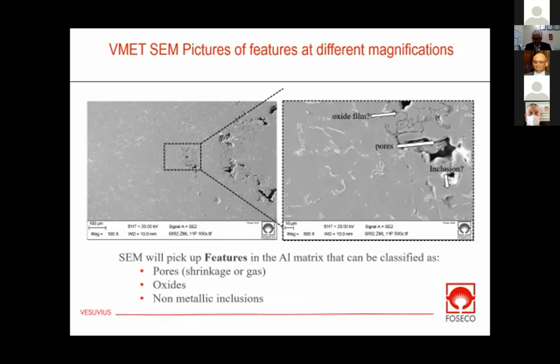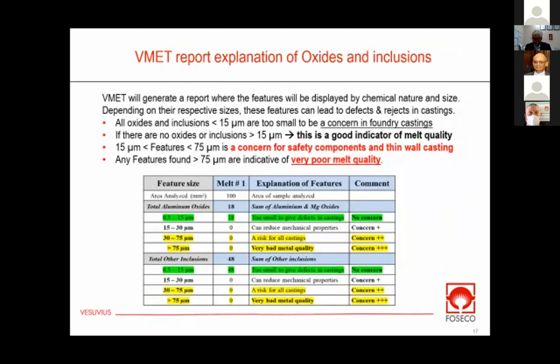So by taking this sample, we are able to help foundries, give them some kind of a quantitative measure. Now, why do I say quantitative? This is because this software we develop is going to scan the sample and is going to count all of the defects that are found, all of the oxides by nature, by sizes. You can see here that these defects, aluminum oxide or inclusions, will be classified by size, by nature, and by chemical composition.